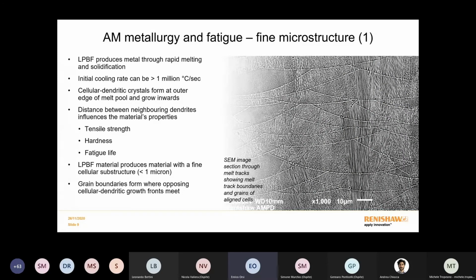In general terms, laser powder bed fusion produces a very fine metallic microstructure. In the image you see on the right hand side, the larger features that you see are the melt tracks and the melt pools, and the finer features that you see are the boundaries and grains of cells that you can see sometimes are aligned in certain specific directions. So this is a positive feature of the technology that improves in general the mechanical properties. It will also pose some interesting challenges about thermal treatments and the performance of the materials in the long term.